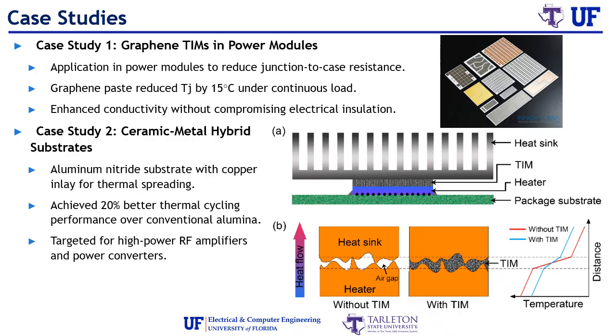Now, we can apply all this knowledge to different case studies. The first case study is based on graphene TIMs in power modules. In this application, the goal is to reduce junction-to-case resistance. You can see it in the first image, where you can see the heat sink, TIM, and heater packaging substrate. The graphene paste reduces the temperature by 15 degrees Celsius under continuous load. This can enhance the conductivity without compromising any electrical insulation or mechanical integrity.